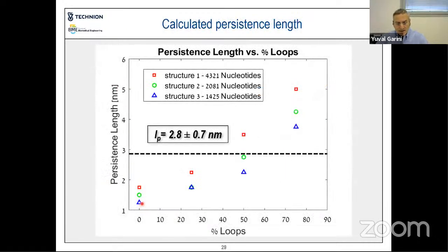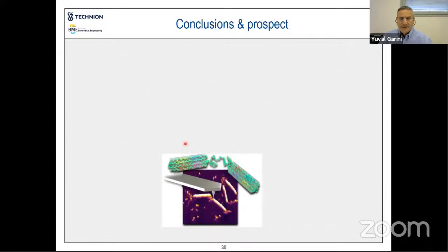And you can see here the results again for, okay, so here we did it for different percentage of the stem loops formation for each one of those 3 structures that you see here. Without entering to the fine details, assuming that 50% stem loops is the more reasonable percentage of stem loops that will be formed, we get a persistent length of 2.8 plus minus 0.7. It's a little bit larger than what we had before, but still very close to that. And that's what we believe is the persistence length of single-stranded DNA.